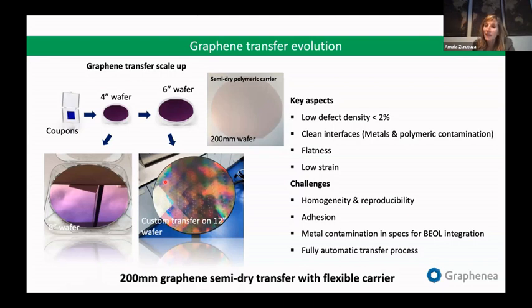Some of the key aspects to take into account in this transfer process: first, if the growth is good, you want the transfer to be good and to have a low percentage of defects. You want also the graphene surface to be very clean. Also, the interface between the graphene and the substrate has to be very clean. If we want this wafer to be processed in existing fabs or semiconductor industry fabrication plants, we need to ensure also the metal contamination is below a certain level. And those requirements are quite strict. So there is a lot of work also in decreasing metal contamination on the graphene film, taking into account, of course, that we use copper. It is a metal for growing it.